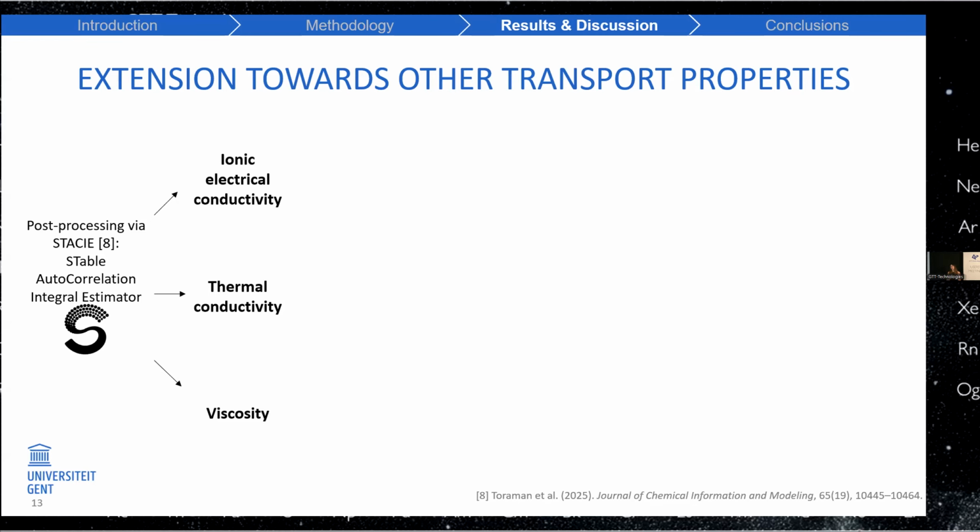And it also allows us to estimate how long our simulations must be to get this reliable estimate. For ionic melts, which are quite viscous, this points towards 10 nanosecond and longer simulations, which is interesting because in the literature previously, MD simulations on slags often only ran for 1 nanosecond. That's often too short to really get a reliable estimate.